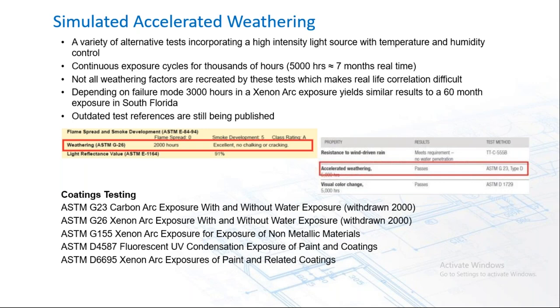Depending on the failure mode, 3,000 hours in a xenon arc exposure chamber yields similar results to a 60-month exposure in South Florida. And that's a pretty extreme environment with UV, salt laden air, winds, and rain. But not all failure modes are replicated using these simulated accelerated weathering tests. And some of these weathering tests are more aggressive than others.